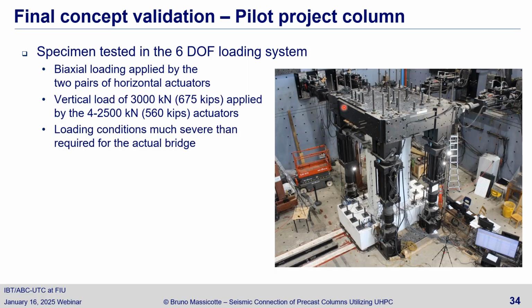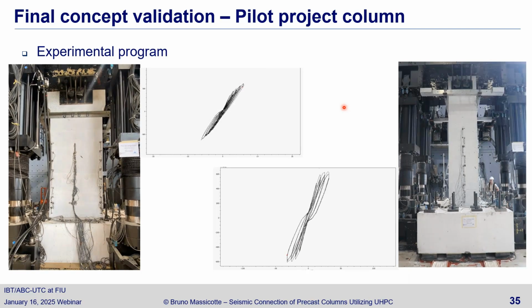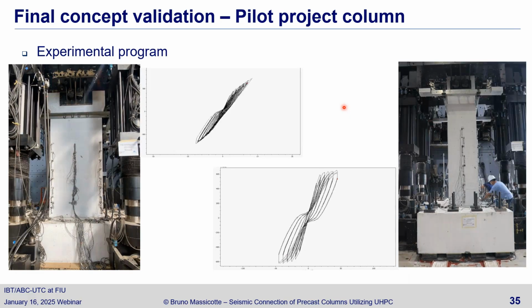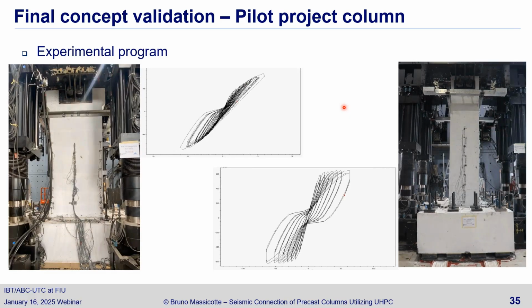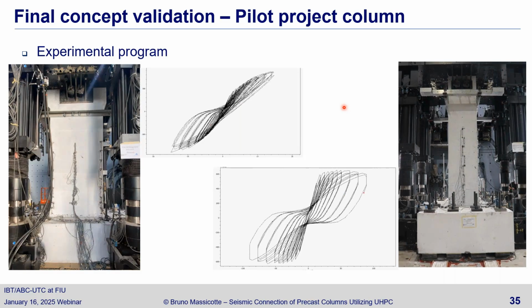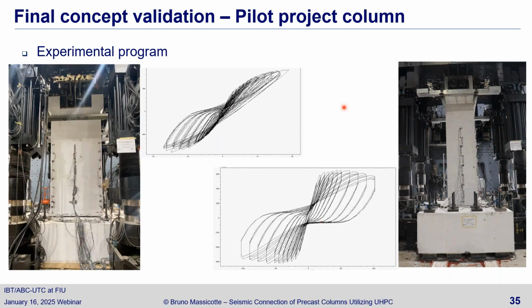So it was tested in biaxial loading for that bridge site. And here I'm showing some behavior of the column during the test. So the test lasted about 6 hours. So we don't work that fast, but you can see that we went to displacement that was much higher than those required for the pilot bridge, and something that will be, as I said, good for a bridge of a much bigger size.